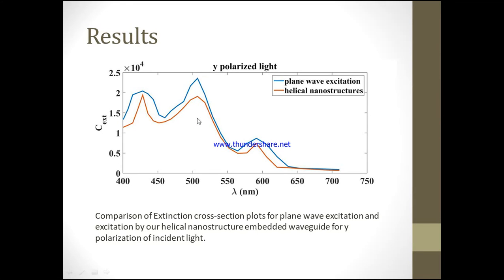The 506.9 nanometer line, which is this one over here, represents the single particle resonance. Now this is indeed sharper and somewhat larger for the plane wave excitation. This has become broader and shorter for our substrate.